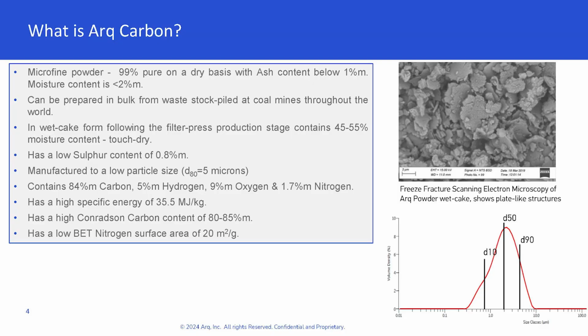So what is the actual Arq carbon? It's microfine carbon, which is highly calorific, 99% pure, with mineral contents of 1% and less. Now, it can be prepared in bulk, which is the attractivity, and we typically produce this in a flotation and milling process where the mechanical presses are used to actually give a pre-feedstock of 45-55% moisture, which is touch dry. So the best example I can give is a consistency of a brownie. So high in moisture, but you can really touch and hold. This is then further dried to get your less than 2% moisture.